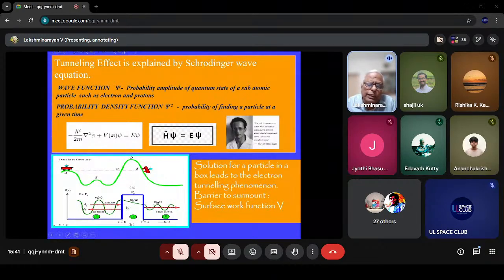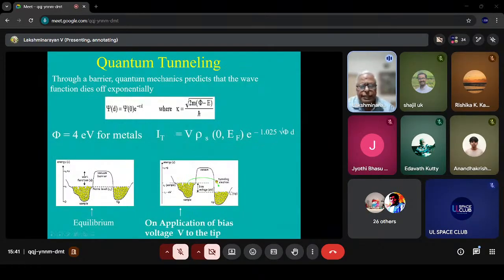So there is a crossover, the electron can cross from one metal to the other metal, even though there is a small gap. The gap is typically of the order of a nanometer. So if that is the kind of gap, you need not have to touch. And if you apply a sort of bias voltage, the Fermi levels of a tip and a sample, and when you apply a bias voltage, the electrons can jump from the sample to the tip. And if you apply the other polarity of the bias, it can jump from tip to the sample, though there is a vacuum gap.